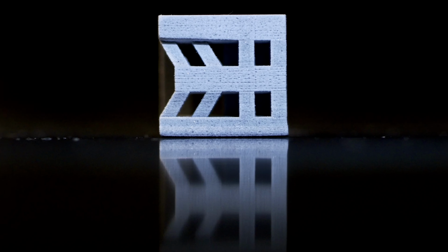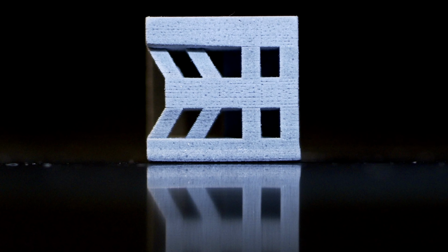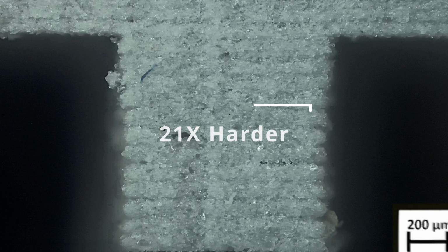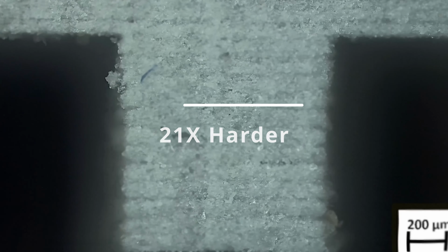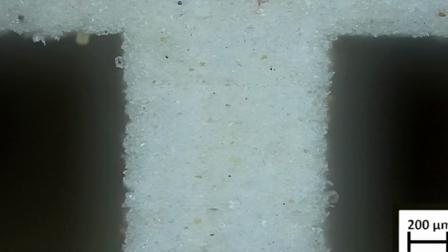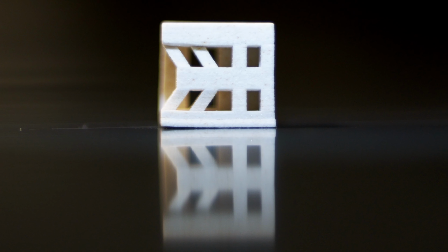The next step is to sinter the part in an ambient air box furnace. This makes the part 21 times harder. During this process, the resin is removed and the particles are fused together. It does not melt. What happens is a solid mass transfer. Due to the law of thermodynamics, the particles want to reduce their surface area energy. They achieve this by merging into each other.